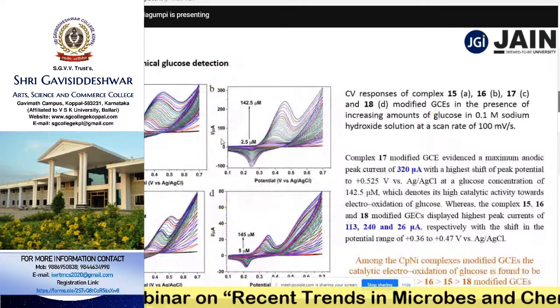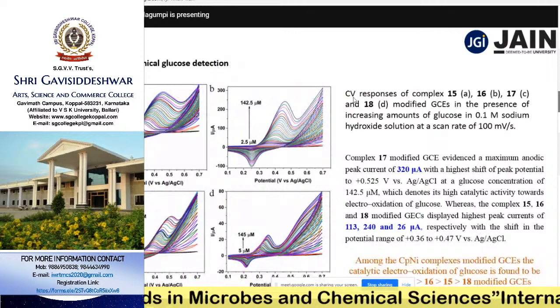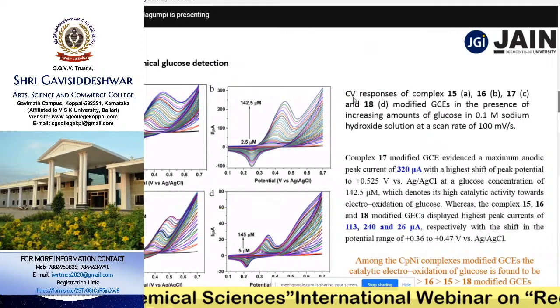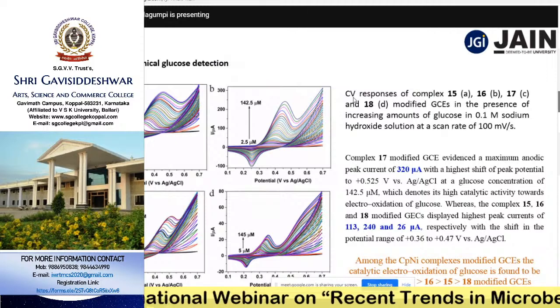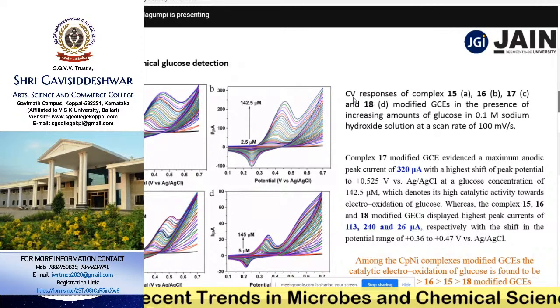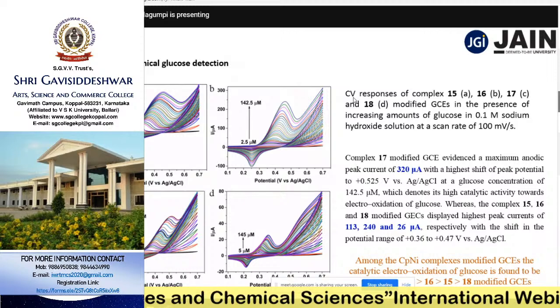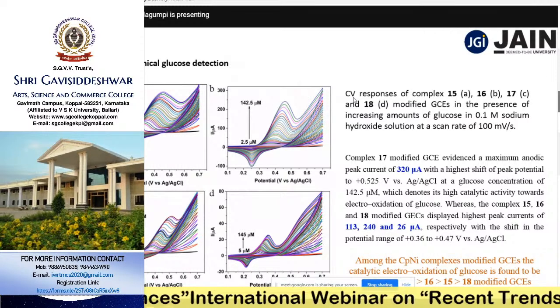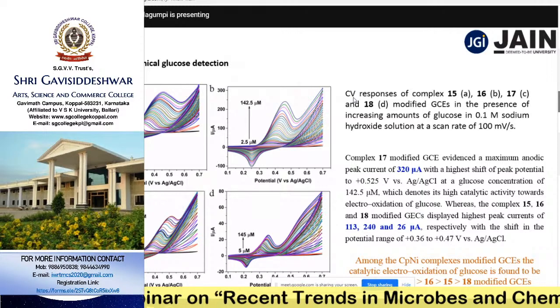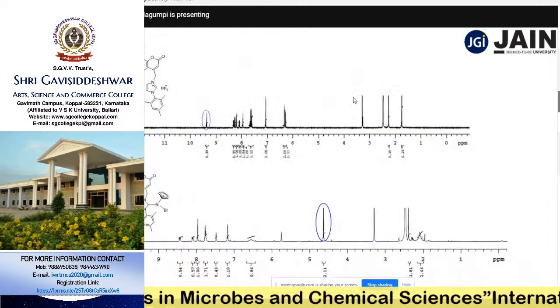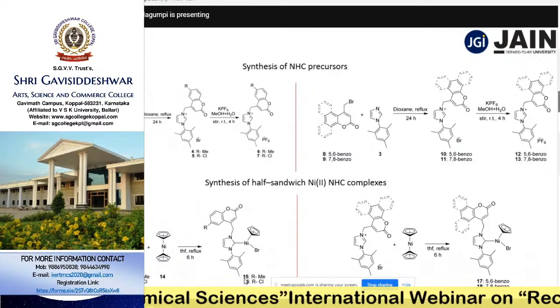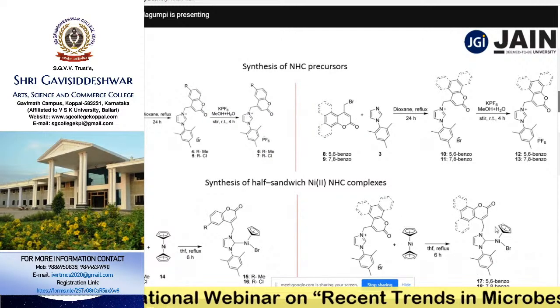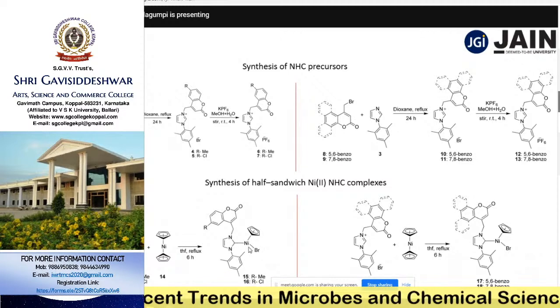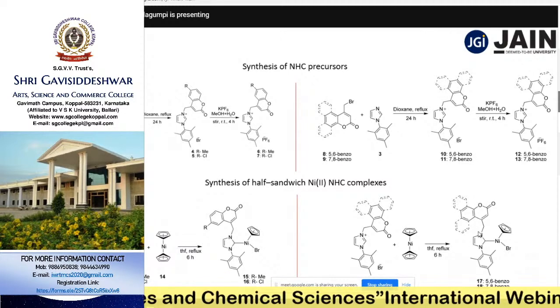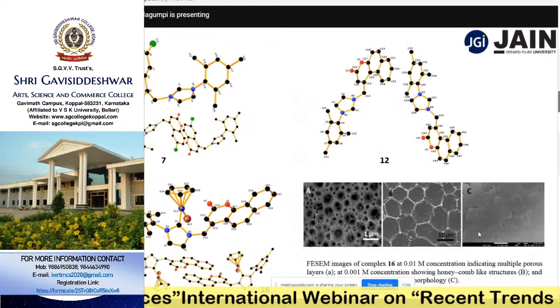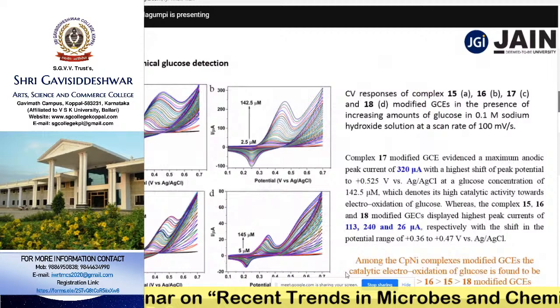Next, electrochemical glucose sensing or detection was carried out. This was done using the CV technique, the cyclic voltammetric technique, which has a typical 3 electrode assembly, in which the AgCl electrode acts as the reference electrode, platinum acts as the counter electrode, and the working glassy carbon electrode is modified with the complexes. We have 4 complexes here: 15, 16, 17 and 18. These sterically modulated and electronically modulated nickel complexes were drop casted on 4 glassy carbon electrodes, and with the help of the CV technique, they have been studied for glucose detection, right?